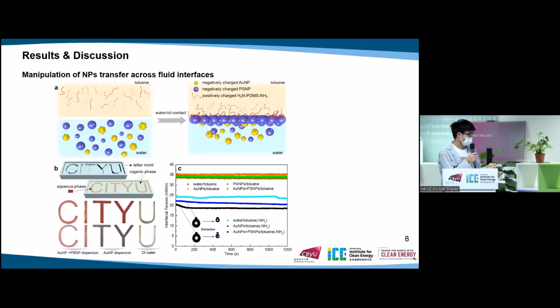Compared to the severe aggregation in the gold nanoparticle dispersion, the mixed nanoparticle dispersion shows no obvious aggregation after contact with the ligands for half an hour. To get more evidence for this, we also conducted the IFT measurements after equilibrium for 20 minutes,